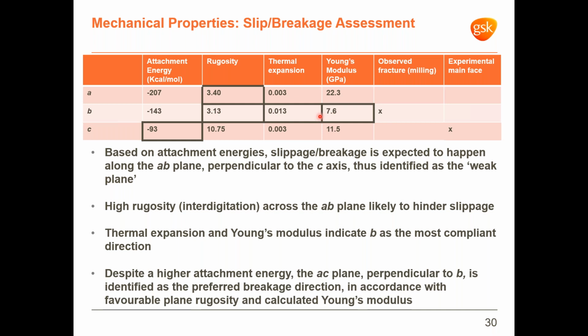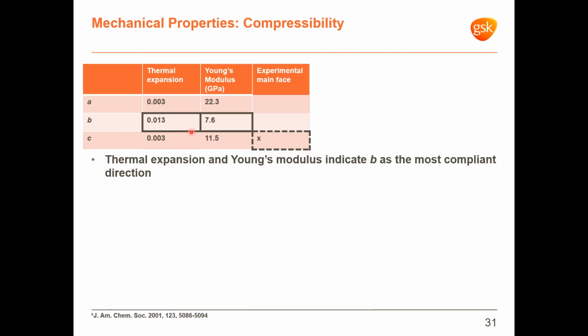In conclusion, despite having only the second lowest attachment energy, the AC plane is identified as the preferred breakage direction in accordance with the favorable rugosity compared to the AB plane with the lowest attachment energy. And in terms of assessing, on the other hand, compressibility, thermal expansion and Young's modulus seem the most relevant indicators, though we are also looking at hardness using AFM nanoindentation as a supporting validating tool.